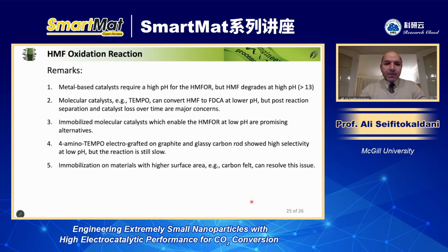So just a summary. We showed that metal-based catalysts require a high pH for HMF oxidation reaction, but HMF degrades at high pH, such as greater than 13. Then, on the other hand, molecular catalysts, not the metal-based catalysts, such as TEMPO, can convert HMF to FDCA at lower pH, but the post-reaction separation and catalyst loss over time are major concerns. So you don't want to lose your catalyst every time that you're running the system. So what we did, we immobilized TEMPO, and we were able to convert HMF to FDCA at lower pH, which is quite promising. And this is where we started.